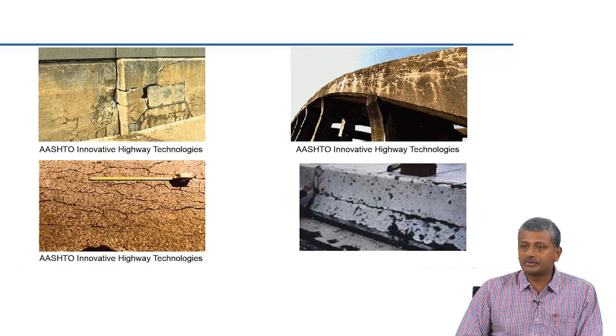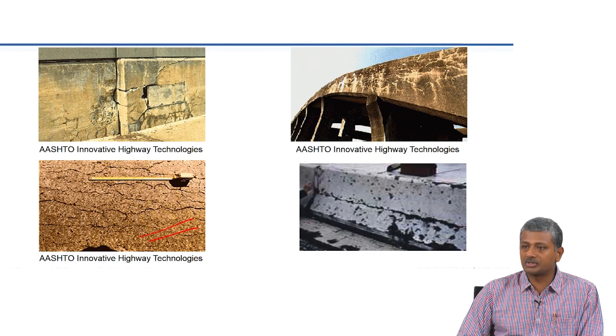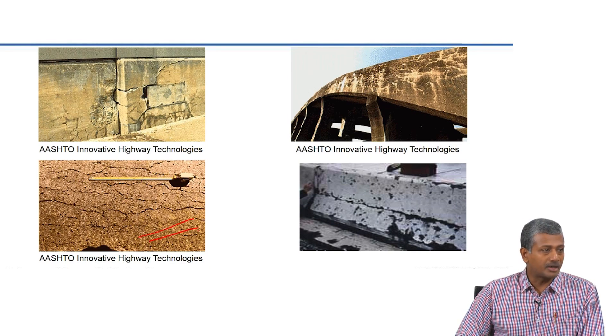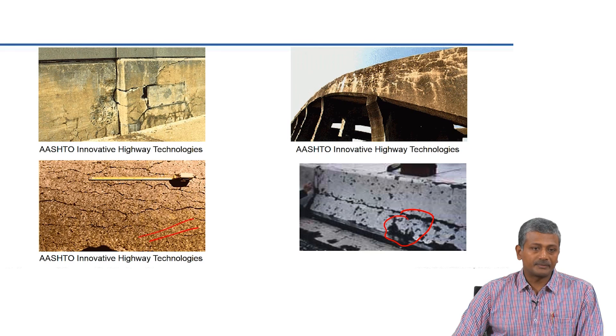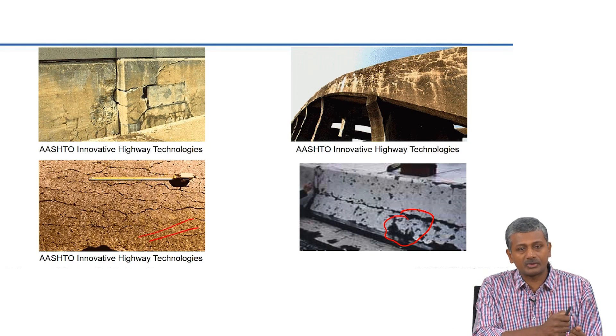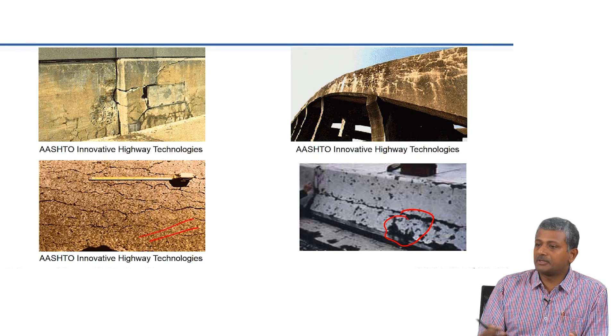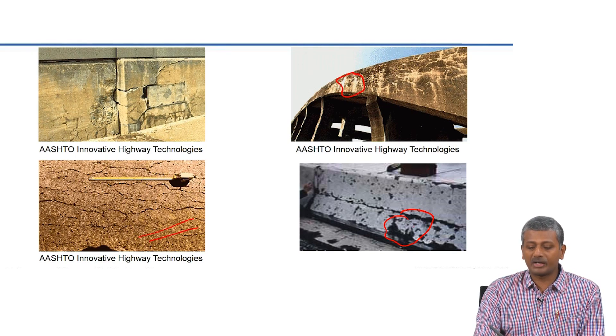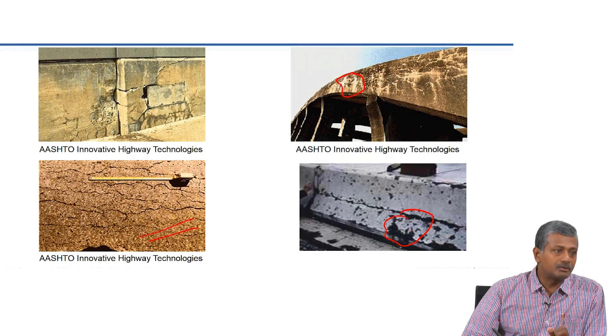These are some examples of structures which have degraded because of alkali silica reaction. The cracking pattern looks quite similar to drying shrinkage — random cracking. But the key difference is that inside the cracks you will see some sort of a black or white product oozing out. That is the ASR gel, usually a low viscosity gel. Originally the gel is white in colour, but after carbonation — exposure to atmospheric carbon dioxide — the gel becomes black. That is how you distinguish cracking due to alkali silica reaction from cracking due to other forms of shrinkage like drying shrinkage or thermal shrinkage.